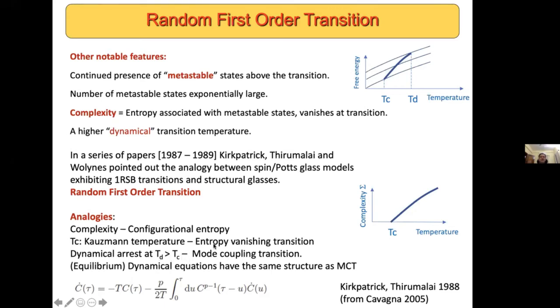And this Td is related to the transition temperature of mode coupling theory. And indeed, the dynamical equations that one writes for these spin models, which I've written down here just for reference, but I won't discuss it, but they basically have the same structure as mode coupling theory.